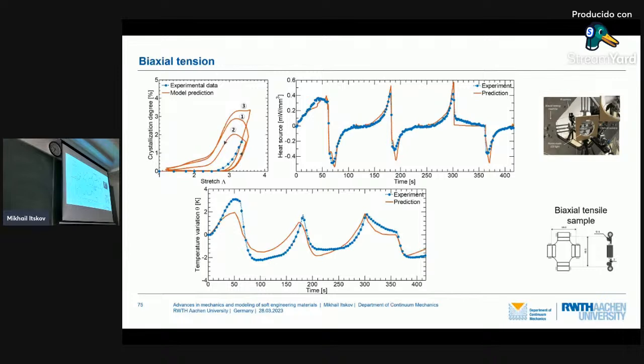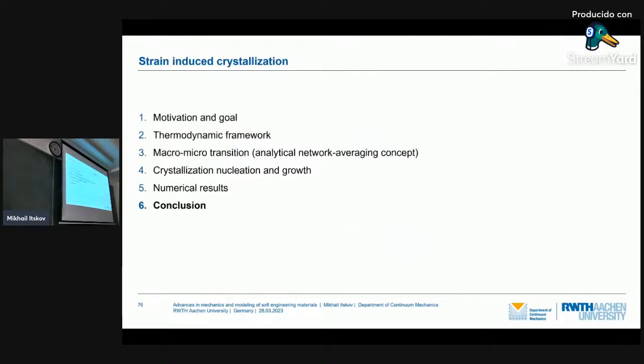And finally, these are the results for biaxial tension. We see here the sample for biaxial tension, simultaneously stretched in both directions, and the results are also rather good, for example, for the crystallization degree. An interesting message here for biaxial tension: we observe that crystallization appears in biaxial tension earlier and at lower stretches in comparison to uniaxial tension.